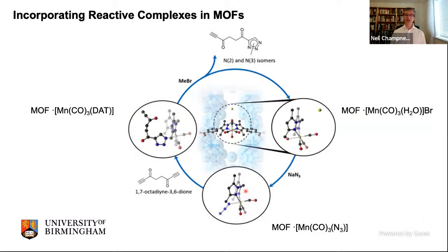So overall, what you're doing here is we're starting with our MOF-supported manganese complex. We react it with an azide, we react it with an alkyne, and then we can liberate the subsequent triazole species by reacting with methyl bromide, which goes back to our original species. And in principle, you can go round this cycle. So we went round it 2 times. You could go longer. There's some degradation over a period of time, but basically you can do this.